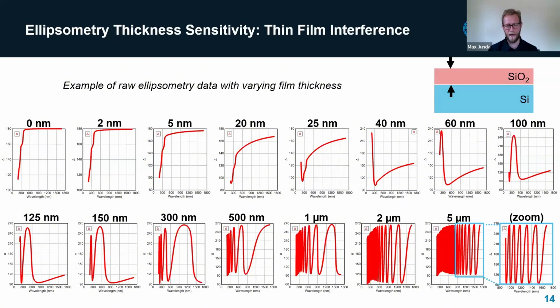This is a slide that I added because I wanted to give, hopefully, an intuitive understanding of how the raw data that we collect actually gives you sensitivity to the thickness. And so what I did is I took a really simple case. This is a silicon substrate and it has a silicon dioxide layer on top. And I just simulated what the raw data is that the ellipsometer is going to measure for a whole bunch of different thicknesses of the silicon dioxide, this whole sequence. So on the upper left-hand corner, you can see 0 nanometers. That means there is no film. That's just what we would measure if it was bare silicon.